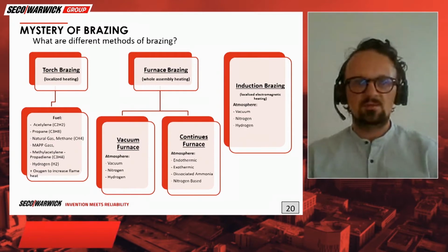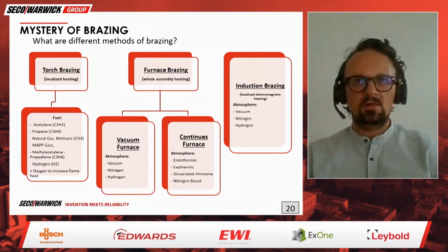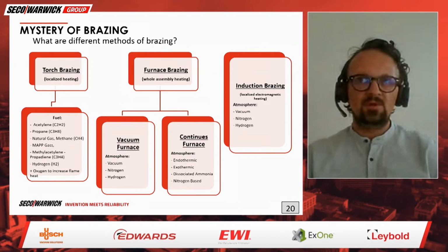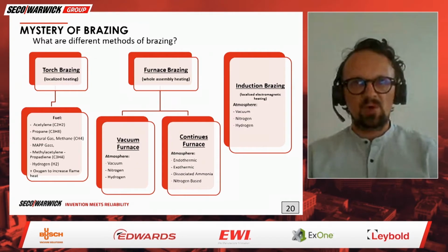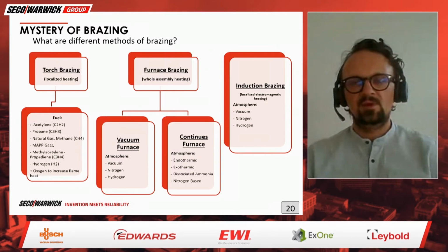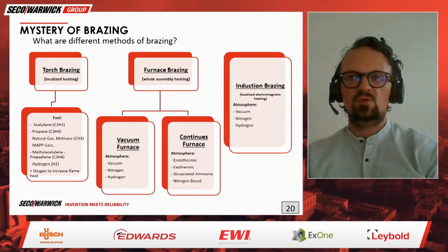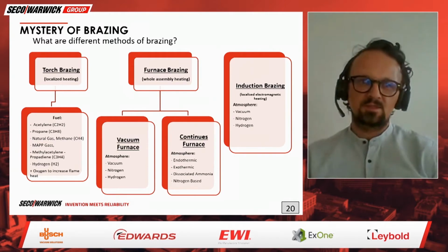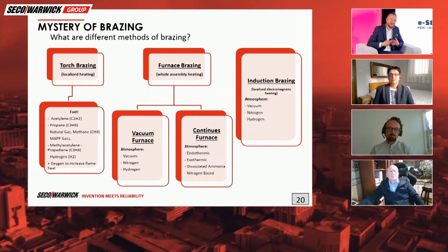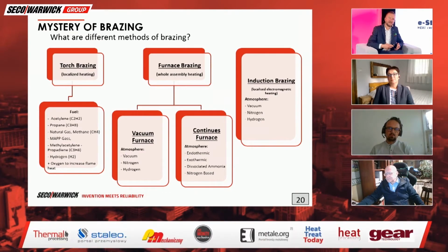And the same situation we have with torch brazing, where we locally heat the parts, and of course you can heat a little bit wider space with the torch and with induction, but that will require a different tool or technique. With the furnace, you heat up the whole part, and the heating is very uniform, and heat distribution is quite important for brazing. As you may expect, I am a big fan of furnace brazing, and sometimes it's a benefit, sometimes a disadvantage, heating the complete component together, not only the brazing place, but the complete element.